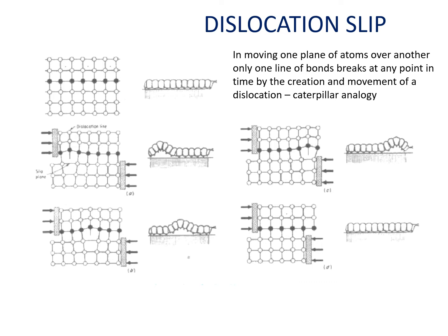I'm going to make this pointer smaller if I can. I can't. I don't know how to make it smaller. We don't break all of the bonds at once. But if we break them all at once to shove one part of the crystal to the right compared to this part of the crystal, that takes a lot of energy, a lot of force, in fact, to do all at once. So how materials actually deform is just bit by bit.